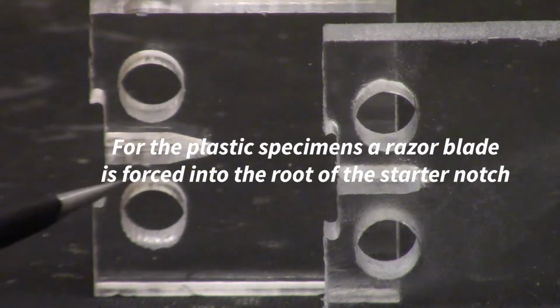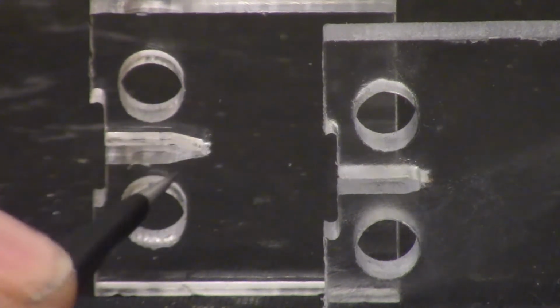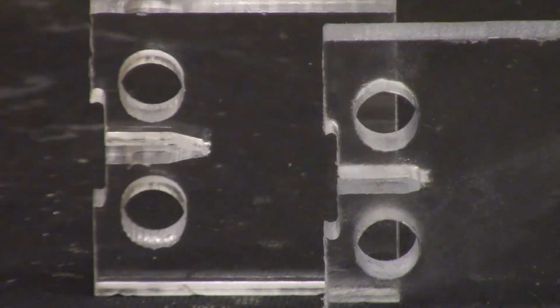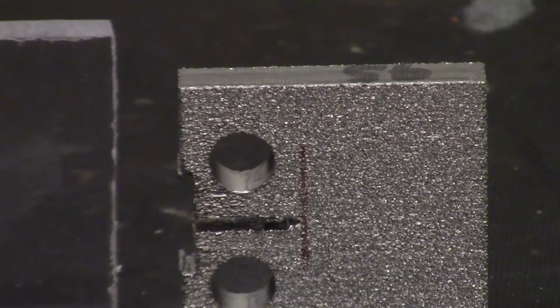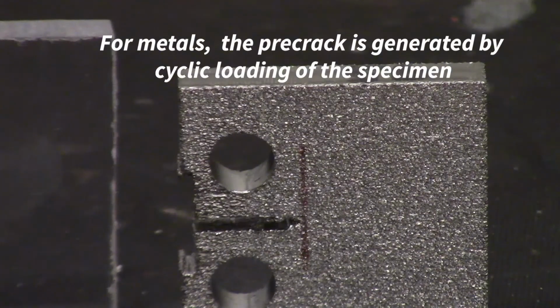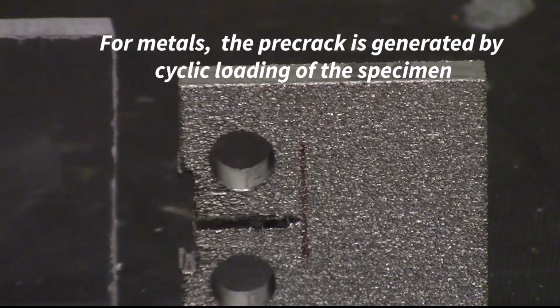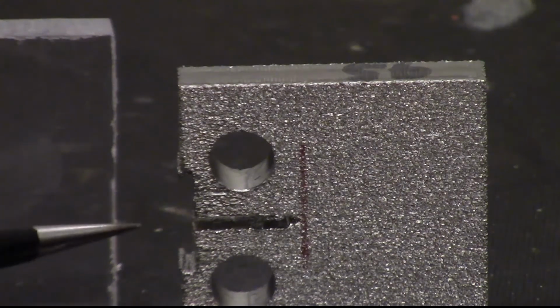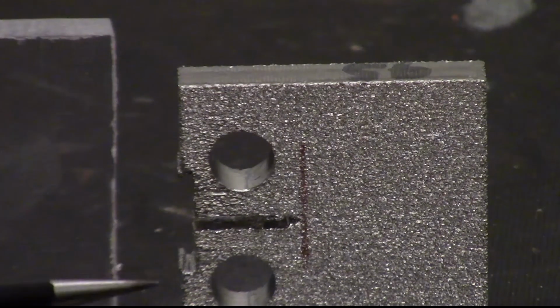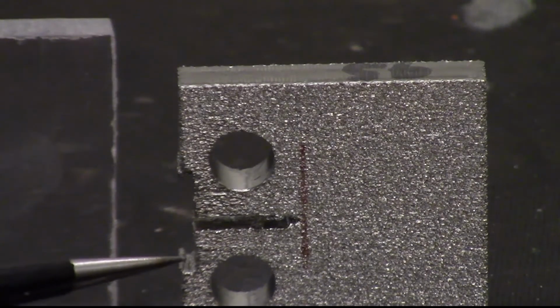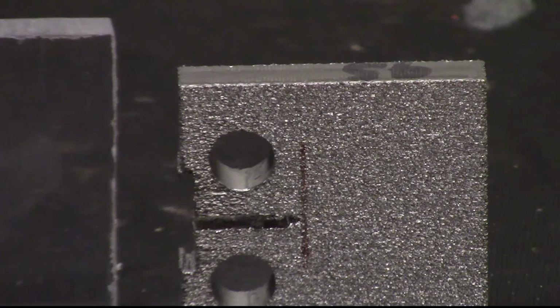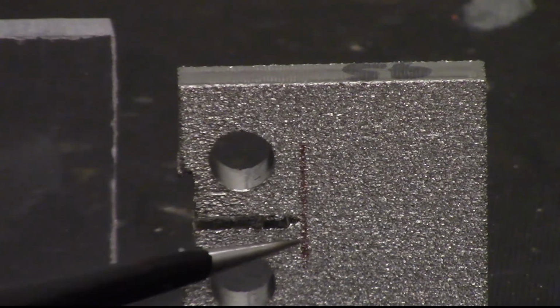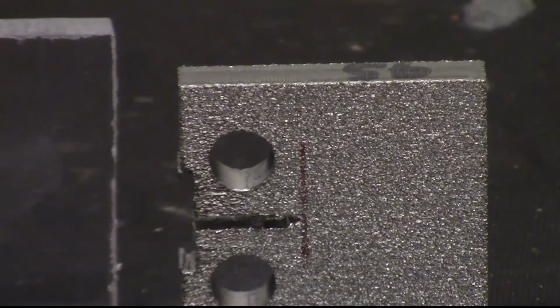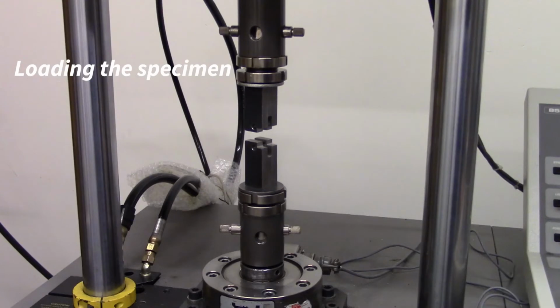For these specimens, all we did was take a razor blade and tap it into the root of that notch until we have about 1 millimeter of pre-crack. To create a pre-crack in the titanium specimen, we have to use the load frame. It's loaded into the machine to a mean load and then cycled above and below that mean load at about 10 cycles per second for as long as it takes to grow a crack from the root of the notch about 1 millimeter out. Now I'm going to load up the titanium specimen so we can get our pre-crack going.